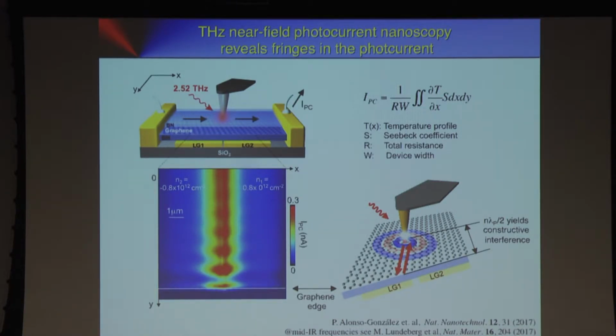And so another possibility is to use a near-field detector. And in this case, we use graphene. I won't go into detail. So that's a graphene sheet, and this graphene supports plasmons. But if one creates a PN junction by having a split-gate architecture, one can create a very strong change in the Seebeck coefficient. And we would then have a local light source, like the one provided by our nanofocus at the tip. We get a local heating of the graphene sheet, and that gives rise to a photocurrent in the graphene sheet. And this photocurrent we can measure here with these two lateral contacts.